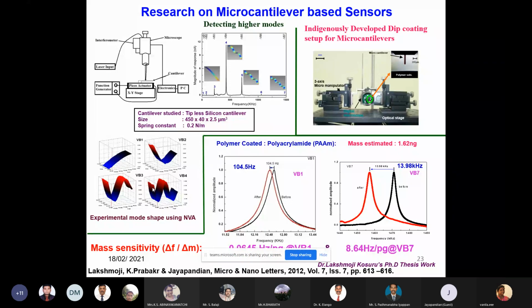Here, the second one is the same coating of the cantilever in the seventh mode of operation, harmonics. We are able to get a fantastic variation, 13.98 kilohertz. For such a high frequency variation, accurate measurement is possible. In that case, 8.64 hertz per 1 picogram addition of mass. Likewise, in vertical bending mode 7, we created a very high mass sensitivity. This result proves how, as in the earlier cases with the simulation results and the coating we observed, by coating practically we are able to get a higher mass sensitivity. That is our result in our lab.